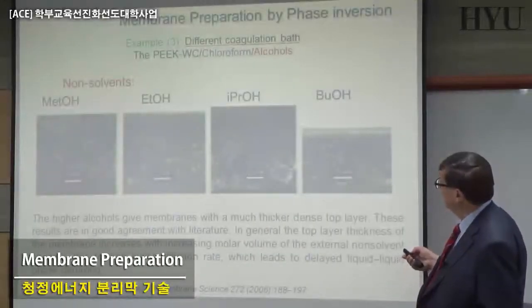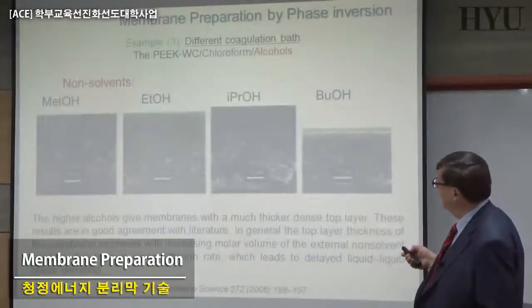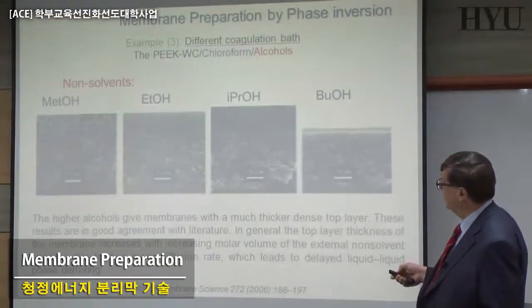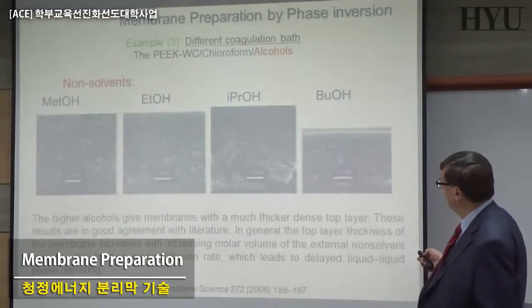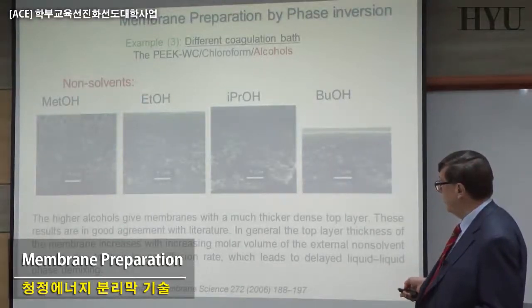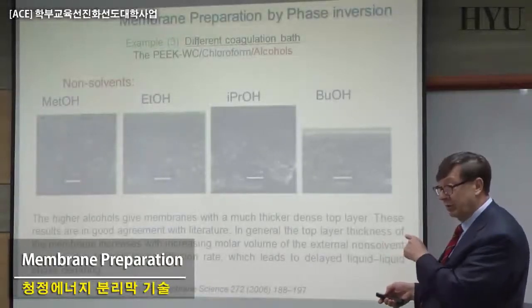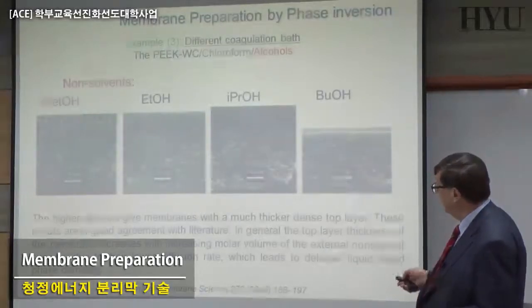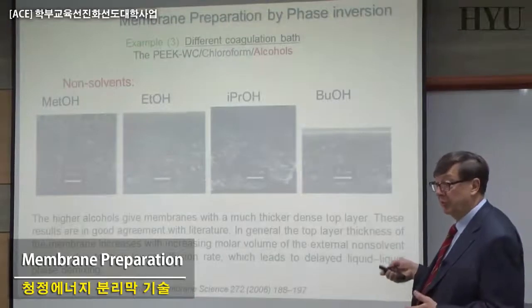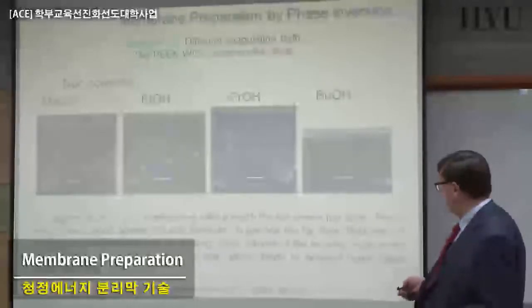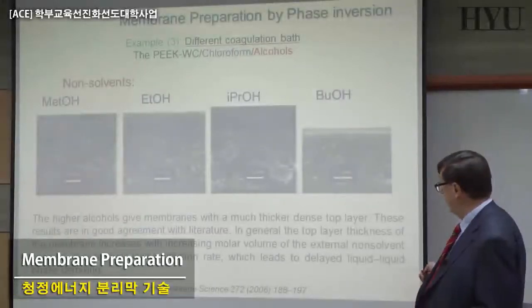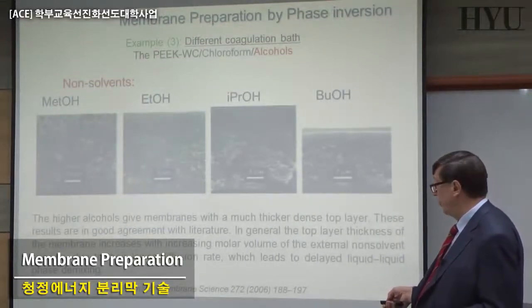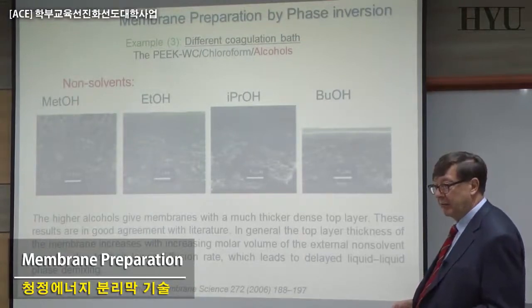Here the same case I mentioned before, the different coagulation baths, that means going from chloroform to alcohols, or different kinds of alcohol, methanol, ethanol, isopropanol, butanol, again. Higher alcohols give membranes with a much thicker dense top layer. So if you know how to do it, as we saw already before, remember with the 3 alcohols, water and alcohol, we can change the thickness of the top layer just by changing this property of the non-solvent, that means the affinity of the non-solvent. The thickness of the top layer increases with increasing molecular volume of the external non-solvent due to the lower diffusion rate, which leads to delayed liquid-liquid phase demixing. So these are all components that are controlling this kind of preparation.